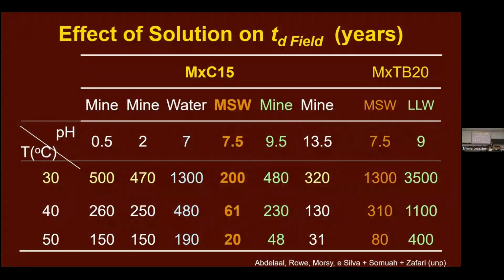MXTB20 is from the same manufacturer with a better antioxidant package and thicker. Under the same conditions, you can see 480 years compared to 3,500. Now, do we believe 3,500? It's a projection a long time out. There are error bars associated with that get bigger the further out you get. But the point is it's a long time, and it's a lot longer than 320.